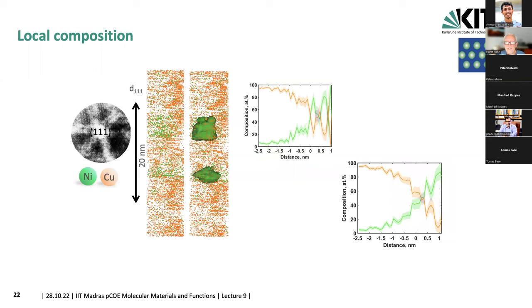So now we can actually determine the local composition. And what you do, this is now computer analysis of the data. You see here the green blob. This is a particle, or I should say it's a surface which corresponds to a certain composition of the nickel. So you could set this to 50 or 70 or 90%. And of course, the higher you go, the smaller this particle becomes, as you can assume that there is some dissolution already of the nickel into the copper, and also the copper can go into the nickel, even at the deposition and the treatment afterwards of the sample to prepare the tip, etc. But still, there are regions where the nickel concentration is 100%.